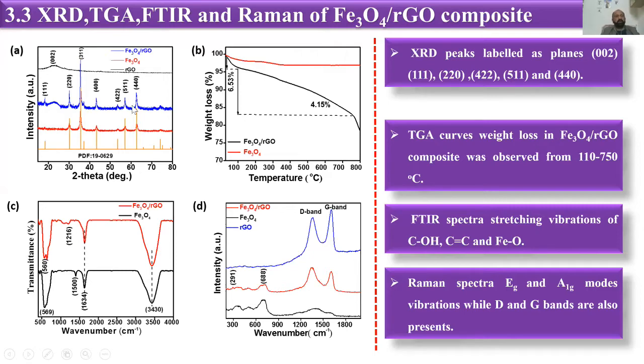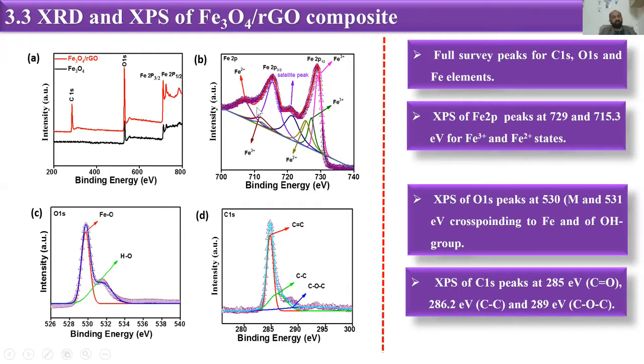So we have done the XPS spectra of our Fe3O4 RGO nanocomposite, and we have got the full survey spectra with peaks related to our carbon, oxygen, and iron elements. And we have done the Fe 2p spectra, which gives the Fe 2p3/2 and Fe 2p1/2 peaks related with the iron. And we have done oxygen and carbon, and all of the peaks are indexed with our system.